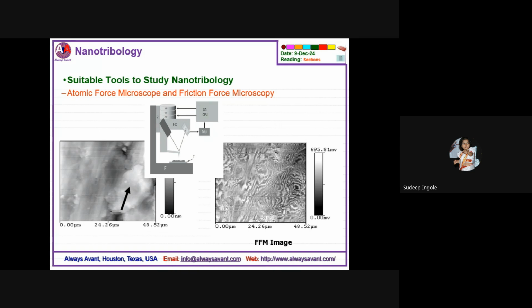If you see, the length of this particular image is only 48 micron. So the image is 48 by 48, around 49 or 50 micron by 50 micron area being scanned, and how the friction changes over that particular cross section is also given in the right hand side image. This is the atomic friction force microscopy image, showing how the friction or the surface behavior of that particular surface varies